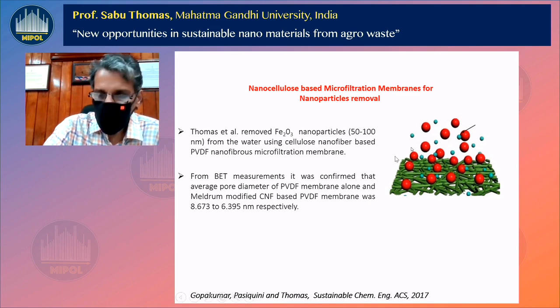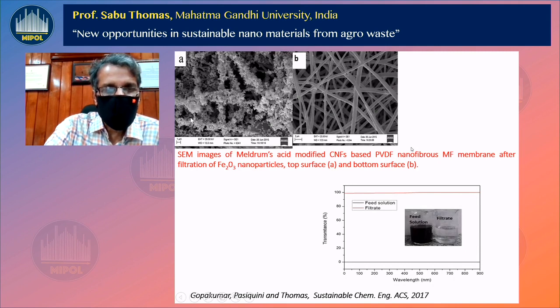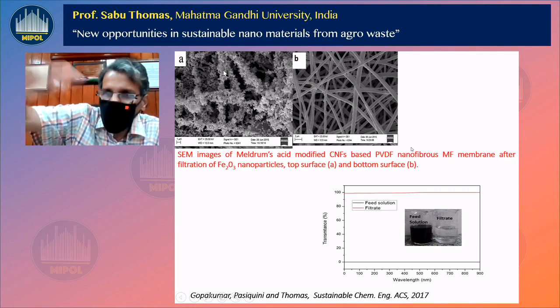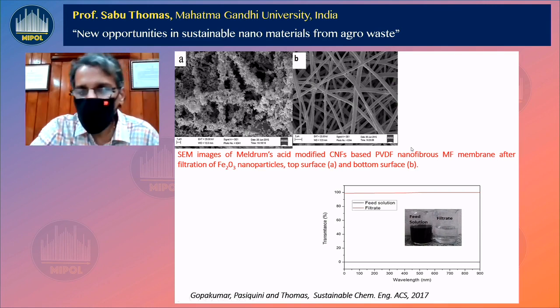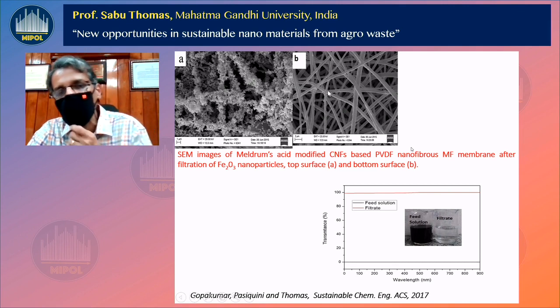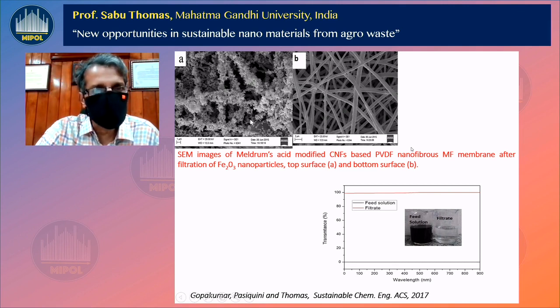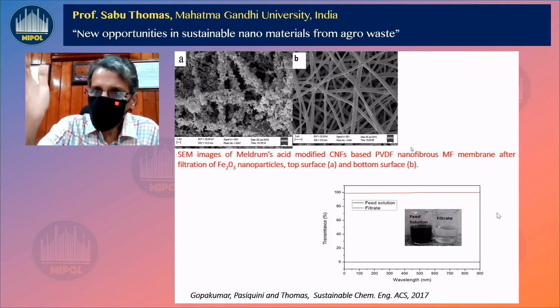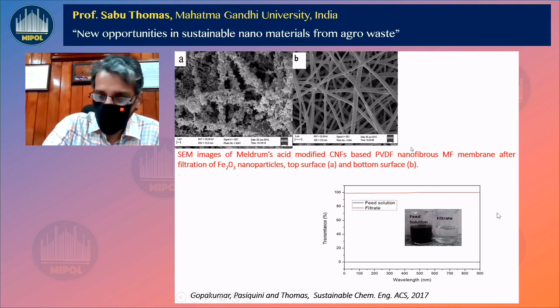Look at this. I will show you a separation picture. All the suspended particles in water will be retained by the top of the filter, where you have a coating with nanocellulose. And the base is nothing but electrospun PVDF. Look at this. All this are being retained by the top. Of course, you have to clean this filter to be used. Look at this filtrate. If you look at the feed solution, this is completely opaque. And the filtrate is very clear. You see the transparency of the filtrate. So we are able to remove suspended particles.